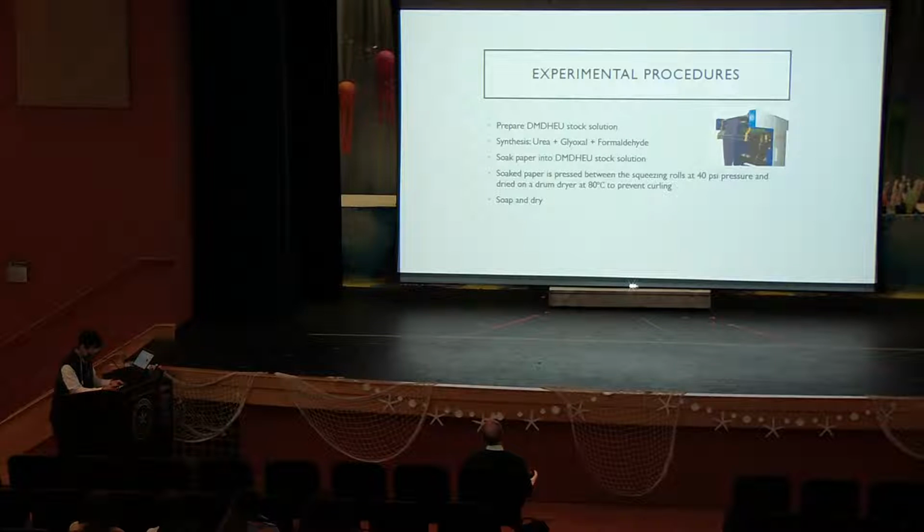Preferably, the mole ratios employed are relative amounts of 1 mole of urea with 1 mole of glyoxal and 2 moles of formaldehyde. Applicants have found that uniformly good results have been achieved by adhering to the mole ratio within the preferred limits. And as indicated, the aqueous reaction medium must be maintained at a pH above 7 and preferably